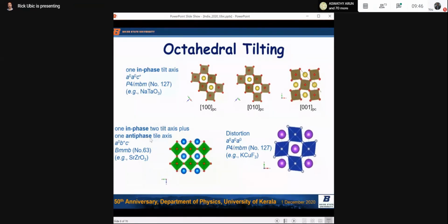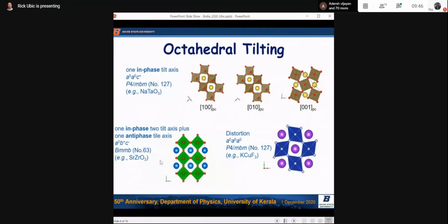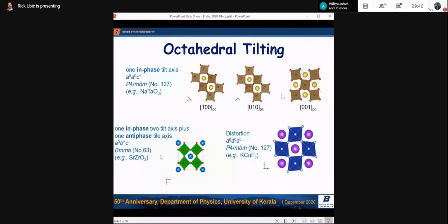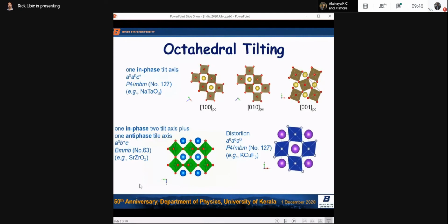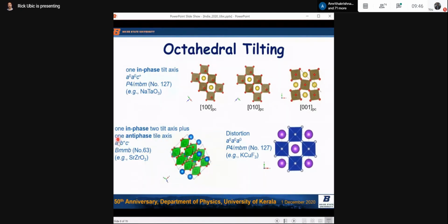Another example here: this phase has one in-phase tilt axis and one antiphase tilt. You can see the antiphase when the animation resets itself. There we go, there's the antiphase. You see the octahedra tilting in opposite directions along that axis. That's the c-axis. And they're tilting in the same direction along the b-axis. And they're not tilting at all along the a-axis. So we have one untilted axis, one in-phase tilted, like this one, and one antiphase tilted, like that one.